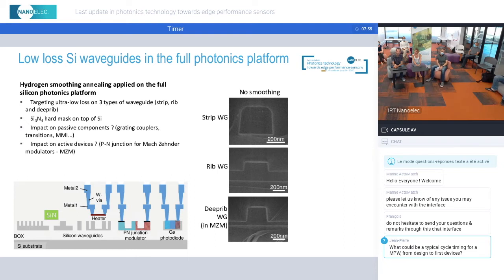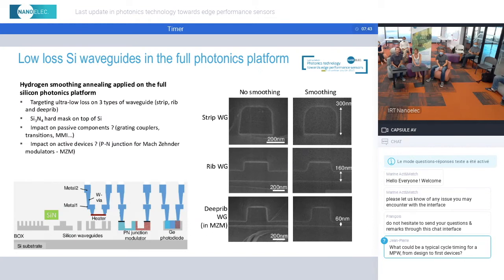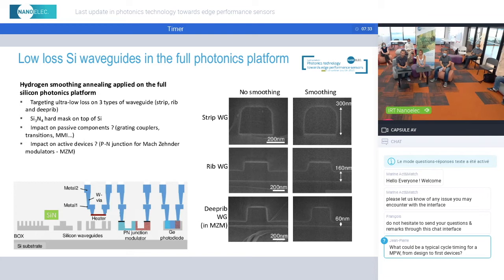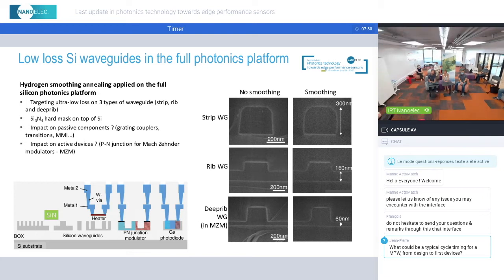So you see on the right side the cross-section of the waveguides without the smoothing, and now you see the cross-section of the waveguides after the annealing. Again, we can see that the shape is preserved by the annealing. It's not the same, the corners are a bit rounded, but the overall shape is preserved. And it's also thanks to silicon nitride hard masks that we have on top of the silicon.